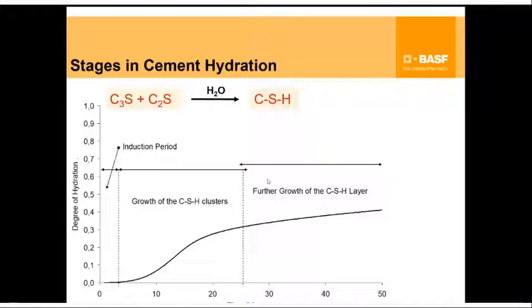So then let me take you through some of the kinetics of cement hydration. What actually happens when cement comes in touch with water? Initially, when the cement comes in touch with water, there is an initial period where nothing much is happening. There's a lot of ettringite that starts to form, like I said, pretty immediately. However, none of the CSH hydration starts early.